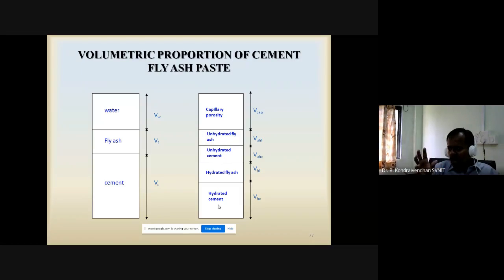So if you know the initial volume, and if you detect the hydrated product and unhydrated product, the cement and fly ash, the remaining thing is nothing but capillary porosity. So one can also calculate the capillary porosity. That's how we calculated the capillary porosity.